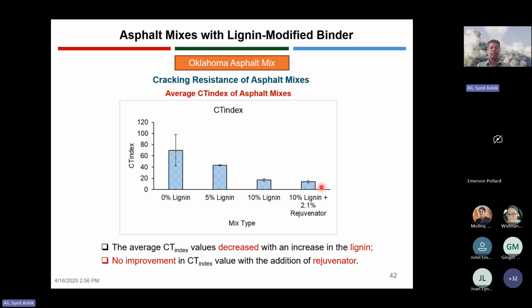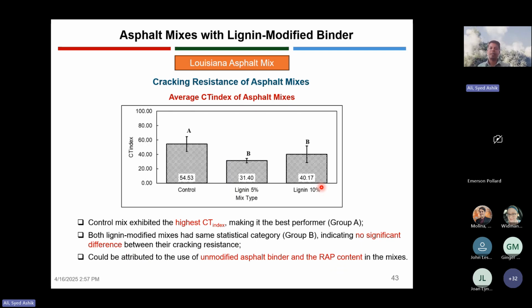We have seen almost the same type of result from the Louisiana asphalt mix as well. They also did the CT index test on the control, 5% lignin and 10% lignin mix. The control mix showed the highest CT index value. The 5% and 10% lignin showed the lowest, but if we look closely, the statistical analysis showed that they are not significantly different.